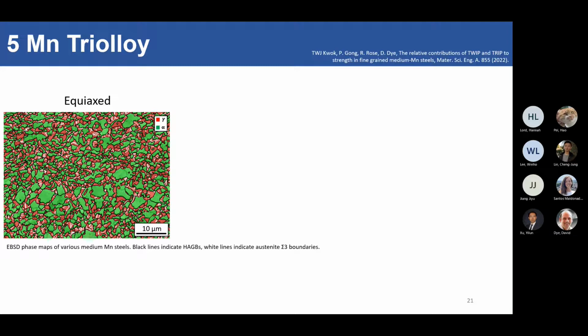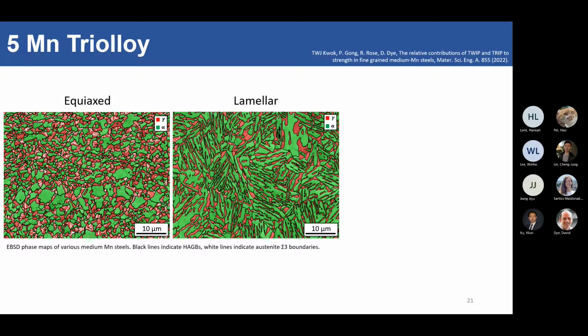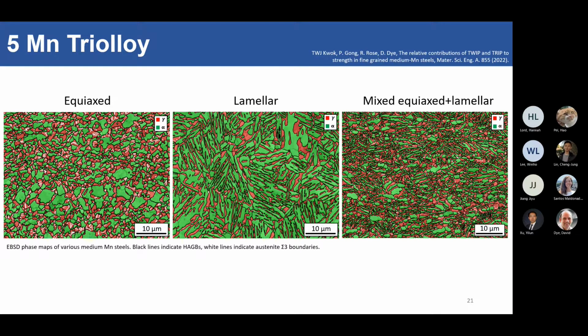The first one being the equiax microstructure, everything very nice and round. So austenite and ferrite fairly interdispersed with one another. Or you could do a lamellar microstructure. So you have alternating lamellae of ferrite and austenite within a prior austenite grain. Or you can have a horrible mix of the two, which is the mixed equiax and lamellar microstructure. So it does look like a mess, but if you sort of squint, the equiax comes from the equiax ferrite grains. You can see the ferrite grains in green are more round and equiax in shape, hence the name. And then the rest of the microstructure is the lamellae that looks like that.